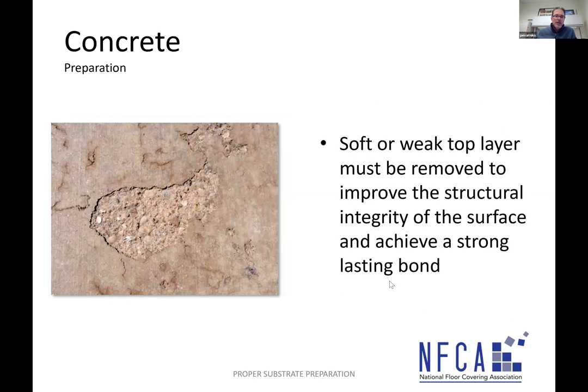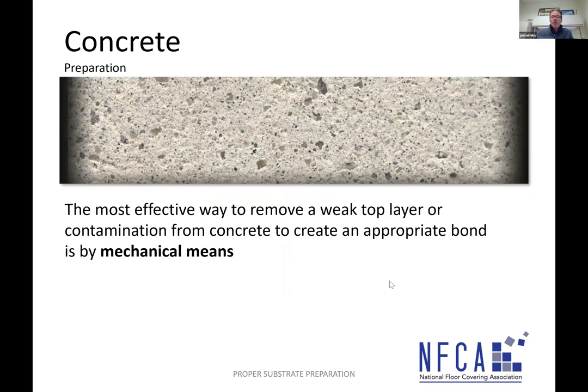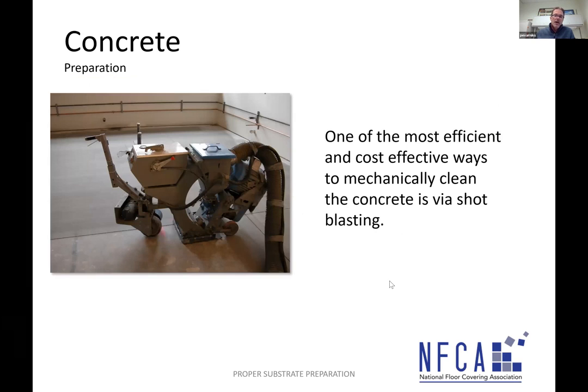You guys walk onto a site and you see concrete flaking like you see here. You've got to get down to the good stuff. That soft or weak top layer is going to cause failure in the patch or leveling material. The most effective way to ensure that you're down to clean, solid concrete is by mechanical means. There are several methods of mechanically cleaning concrete. One of the most efficient and cost-effective ways is shot blasting.